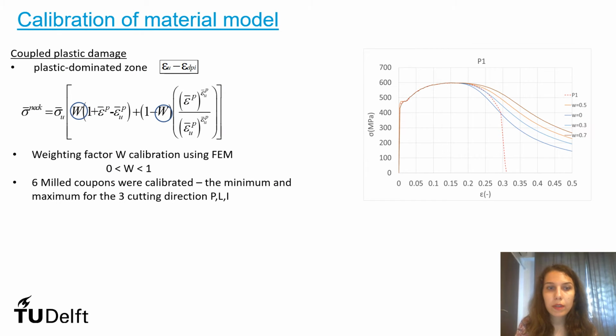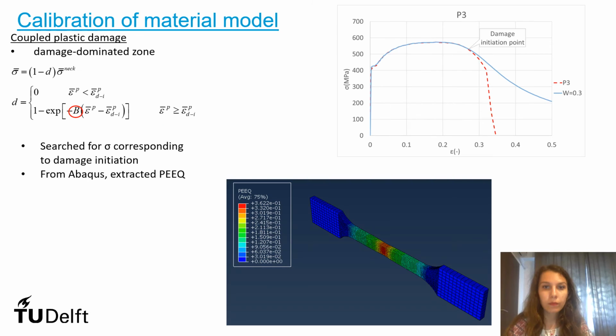In the coupled plastic damage, plastic dominated zone, the weighting factor W takes values between 0 and 1. I calibrated the weighting factor using finite element method. I calibrated 6 milled coupons, the minimum and the maximum for the three cutting direction, which is perpendicular, longitudinal, and inclined. In the coupled plastic damage dominated zone, the weight parameter W is not enough to describe the damage evolution.